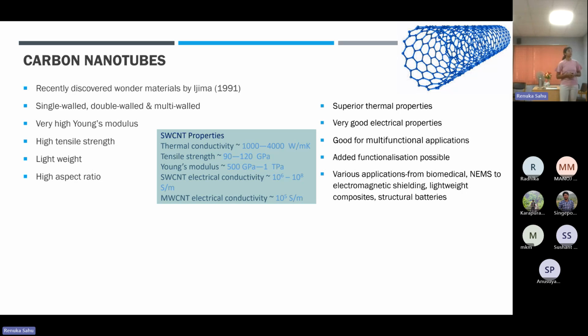These are the properties of the single-wall carbon nanotubes, wherein the thermal conductivity ranges from 1000 to 4000 watts per meter Kelvin. The tensile strength is around 90 to 120 gigapascal, and Young's modulus is around 500 to 1 terapascal. The electrical conductivity is quite good, at 10 to the power 6 to 10 to the power 8 Siemens per meter. And for multi-wall carbon nanotubes, it's slightly less.